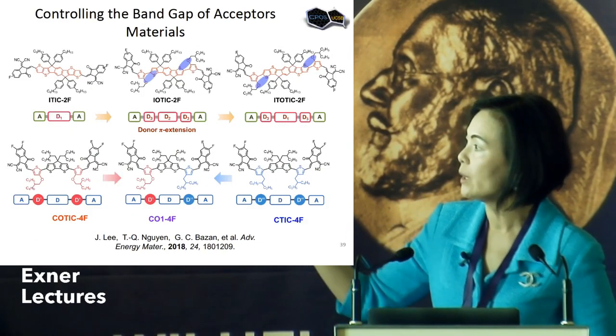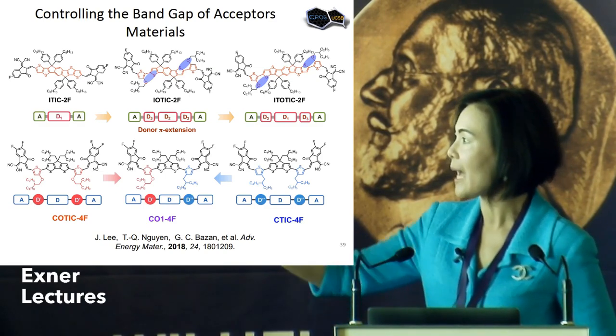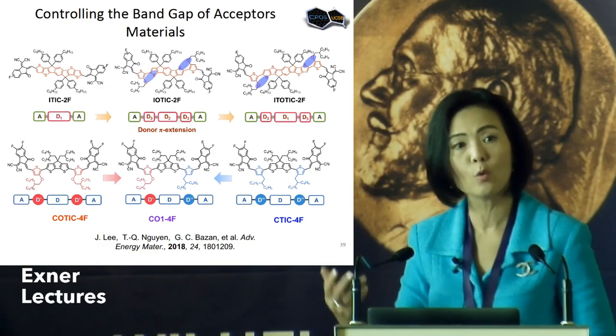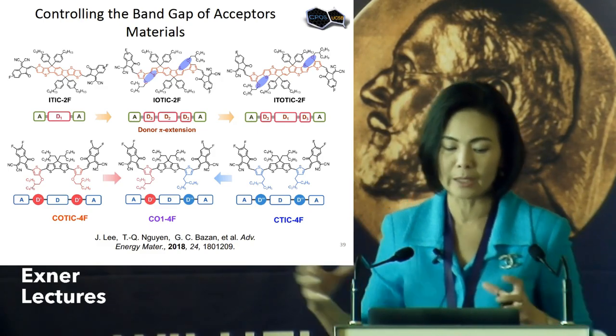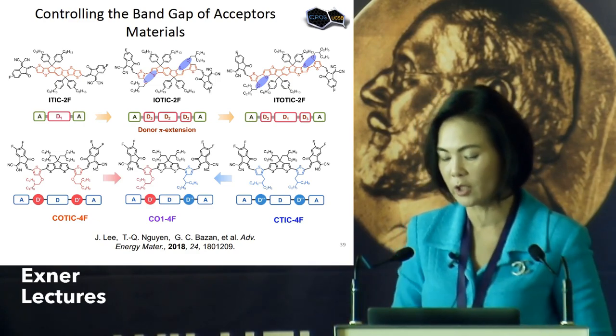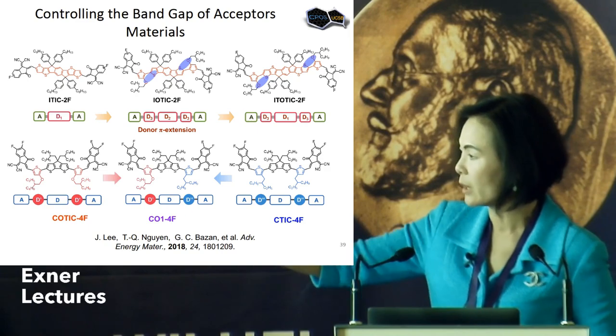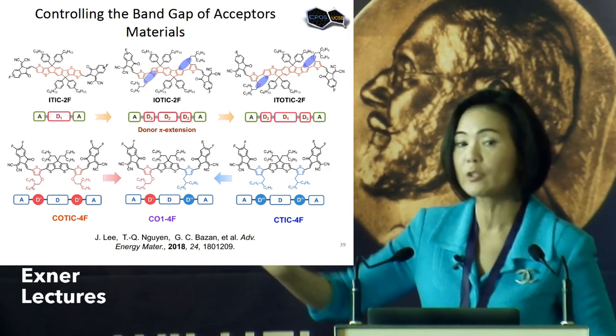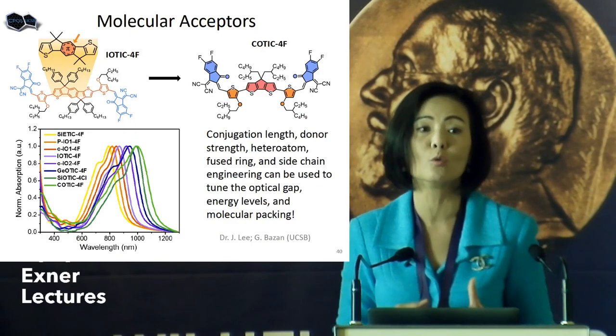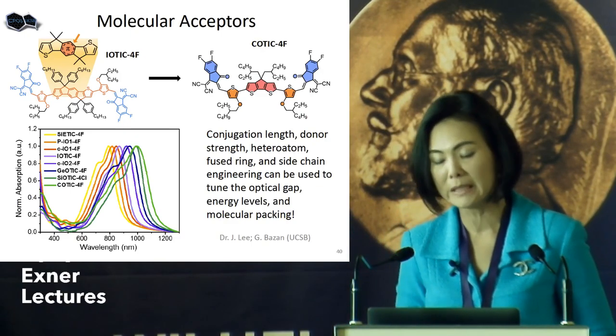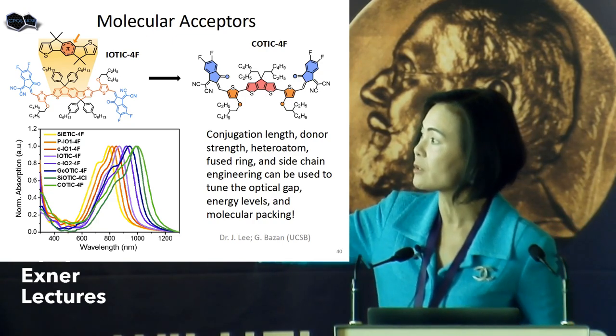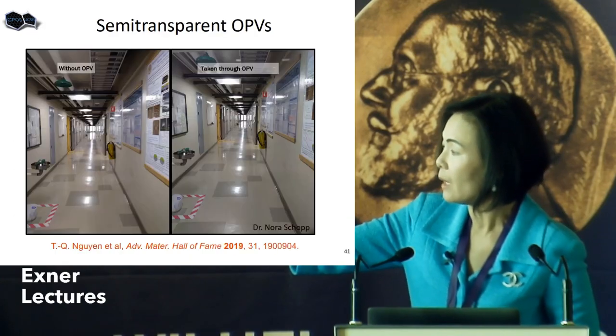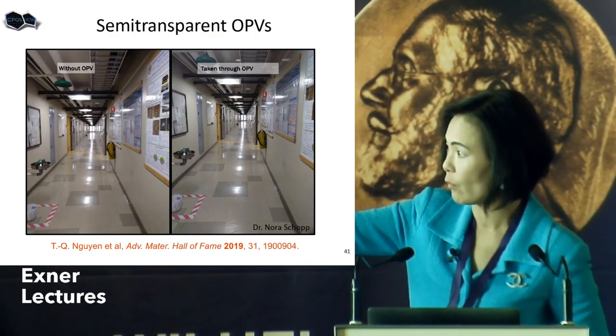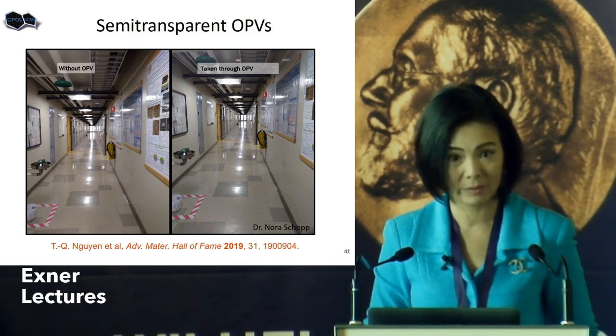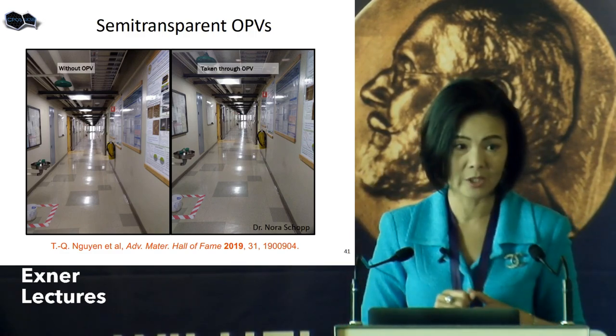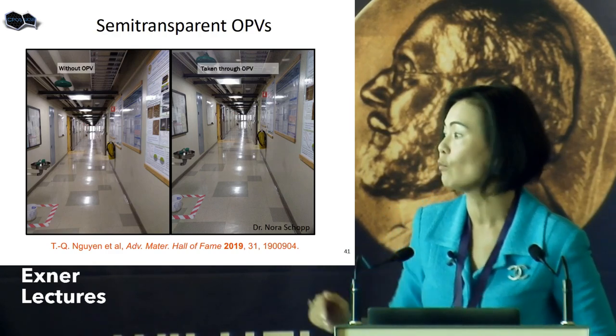So we go on, and together with Guy Bazan's group, we designed a number of acceptor molecules where we can change the chemical structure, so that we can control the band gap and the molecular morphology of the material. So you can see here, we can tune the band gap of the material quite a bit. And by doing that, that allowed us to make semi-transparent solar cells, for example, for greenhouse application. So this is an example of such a semi-transparent OPV. For the one on the left, we put the camera and take a photo down the hallway of our lab without the OPV. And for the one on the right, we take it through the semi-transparent OPV. And you can see that it looks very, very similar.